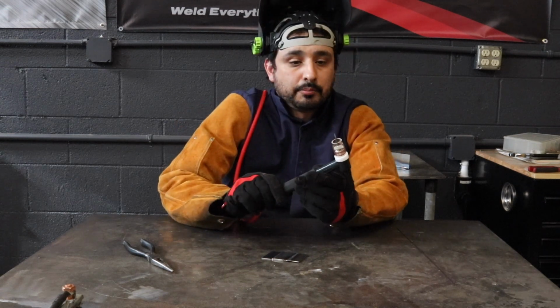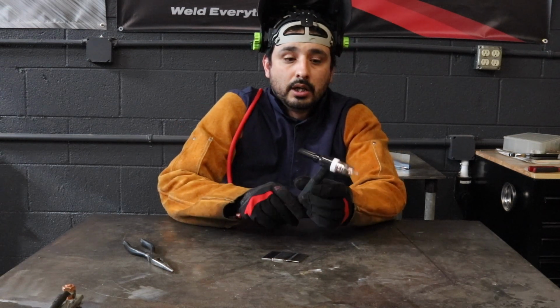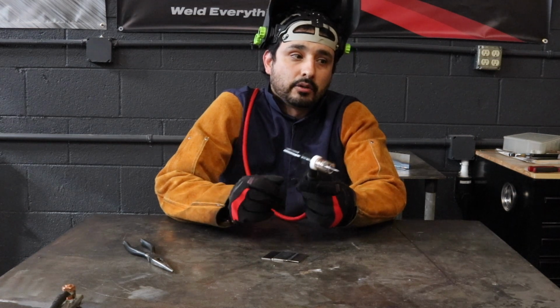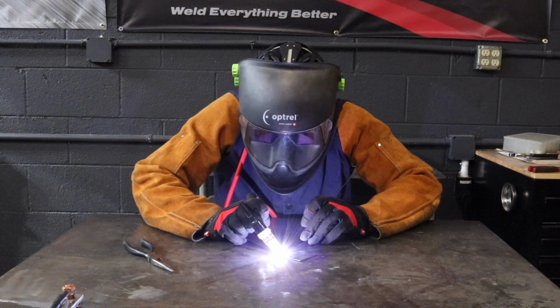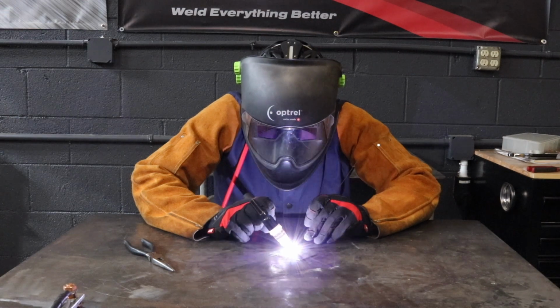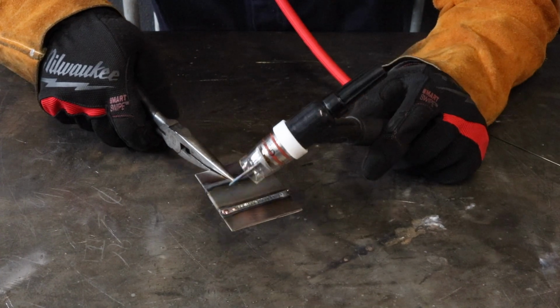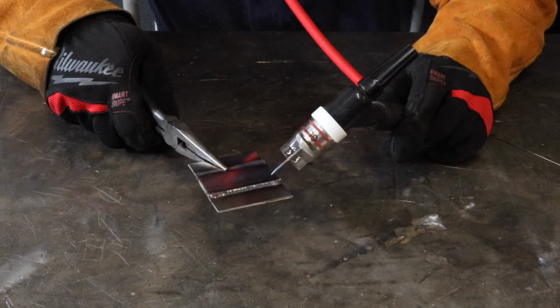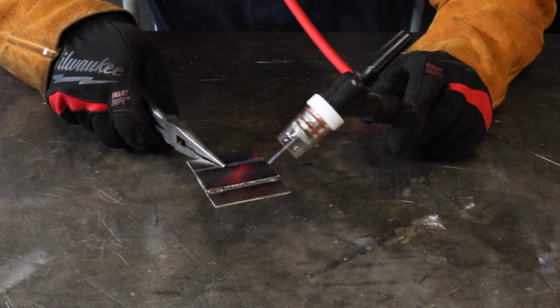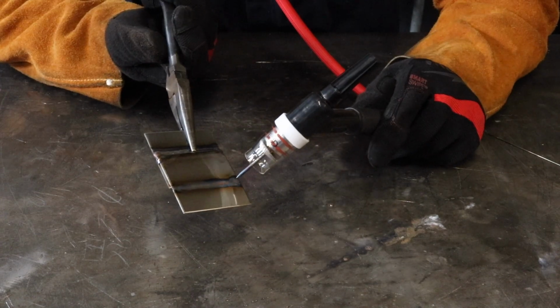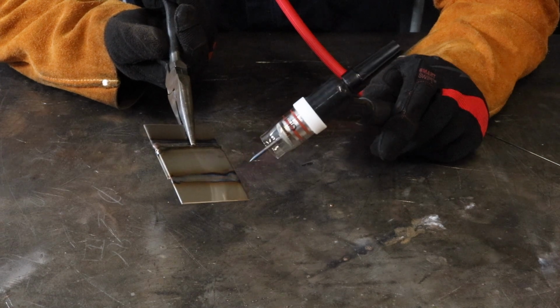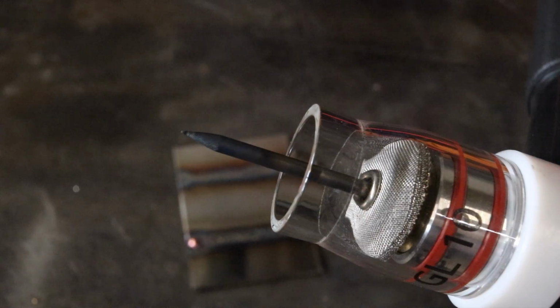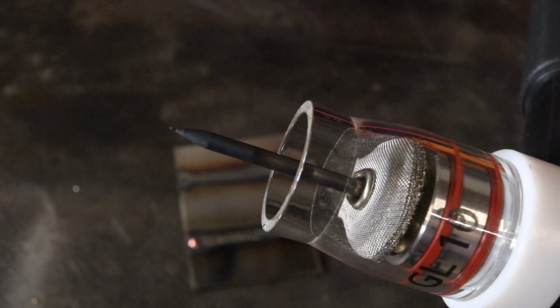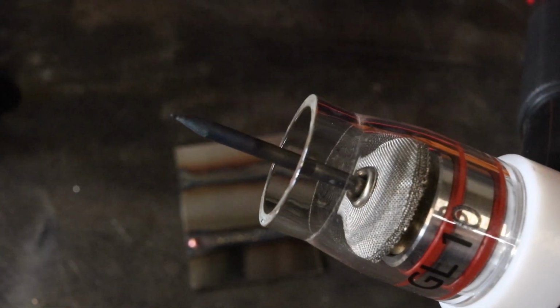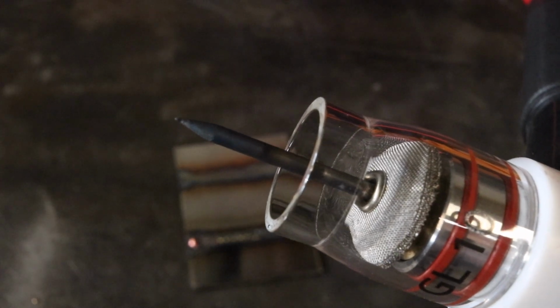We're going to go ahead and put the post flow down and show you what happens if you don't have the accurate amount of post flow. This was the weld I did with 1 second post flow. The weld itself is good, heat affected zone on both sides. Little burn through at the end, and that's because I didn't have that cooled down with the post flow. As you can see with the tungsten itself, the discoloration, the darker hues on it, the lack of post flow is actually causing the tungsten to overheat.